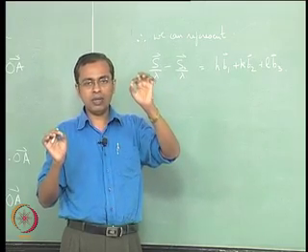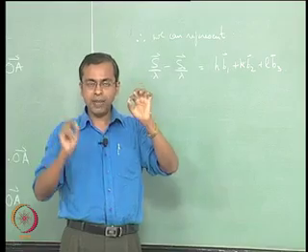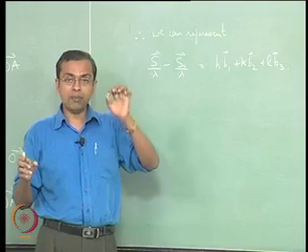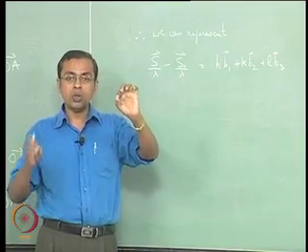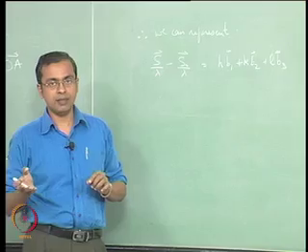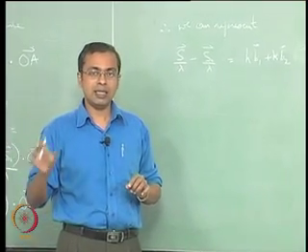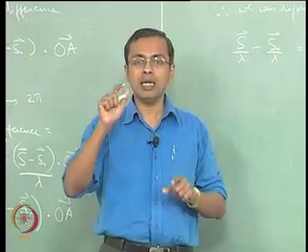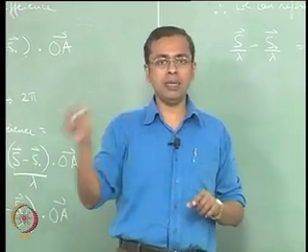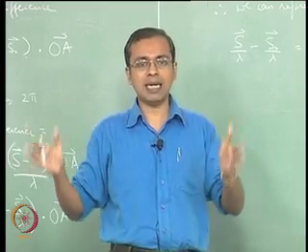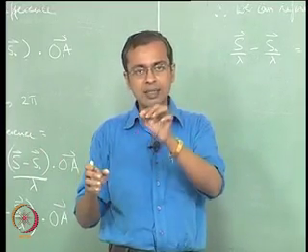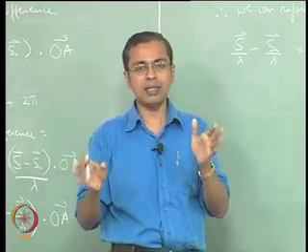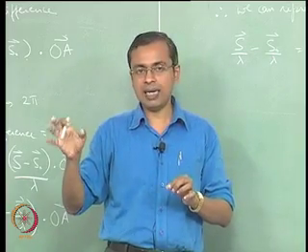Using that we were able to decide on the distance OA as P A1 plus Q A2 plus R A3, where P, Q and R were integers, because that moved us from a lattice point which was O to another valid lattice point which was A. Those were two valid lattice points, therefore OA was a valid real lattice vector. That is the reason why P, Q and R had to be integers, because that is the way in which we define such lattices. When you use integer movements of A1, A2 and A3, you move from one lattice point to another lattice point.